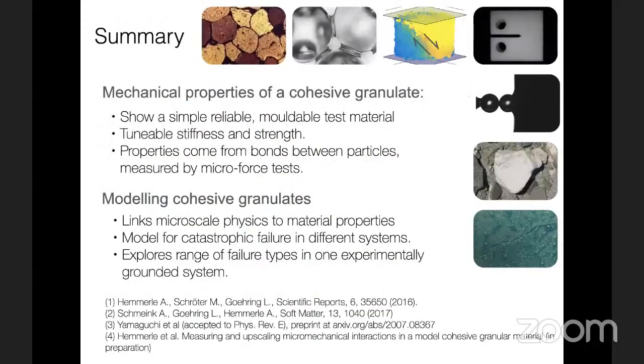So to summarize, what we've done is we've made a material which consists of glass beads held together by polymer bridges. The physics of this is that we have bridges which are soft compared to the particles. And by adjusting the amount of polymer and the stiffness of that, we can change the stiffness and failure conditions of these materials over a wide range. They tend to fail at fairly high strains, of order 0.1, and we can show how the properties relate to the properties of individual bonds between particles.